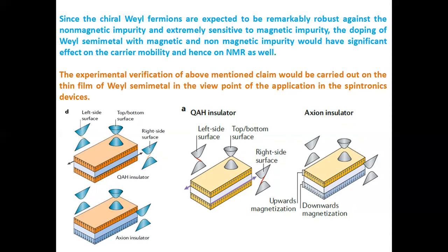But very unfortunately, the formation of the gap is proportional to the temperature, which is in the millikelvin range. That means the topological non-trivial feature of the material will go away if you increase the temperature to, let's say, 50 Kelvin. So at that low temperature, it is almost of no use in our daily life. Because the magnetic exchange energy gap is proportional to kBT, and corresponding to that gap your temperature can be tuned. If that gap is really small, in milli electron volts, obviously you don't expect that topological non-triviality to sustain at a high enough temperature.